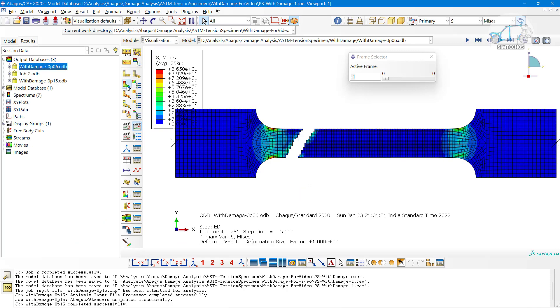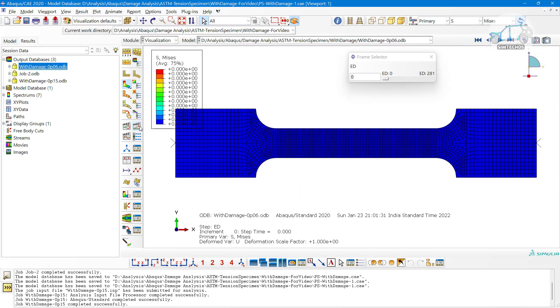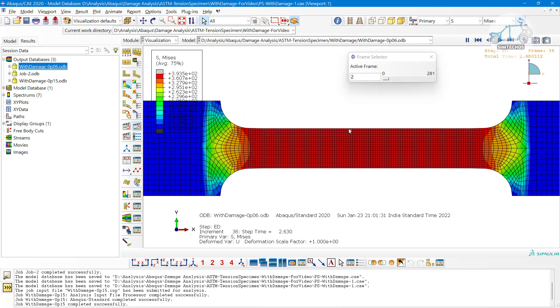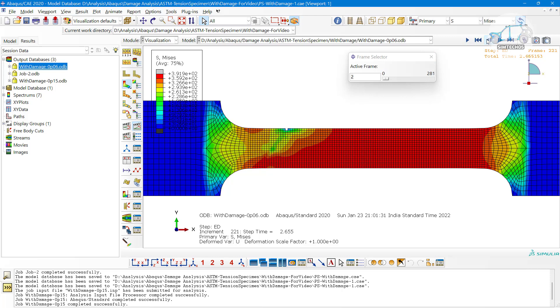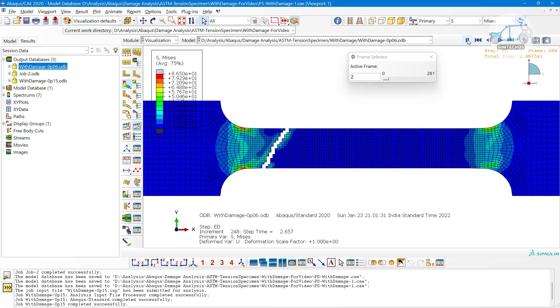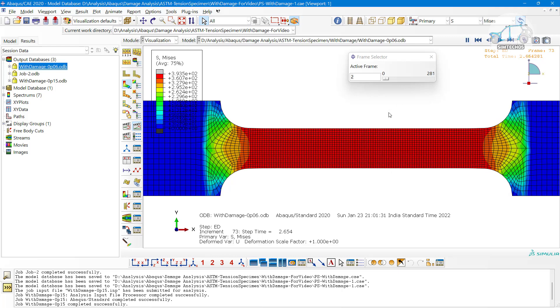So this is 0.15 for the second case. You will get a pretty accurate result. If you want to see the simulation behavior of both cases: in case one, once the load is sufficient enough to develop strain more than the fracture strain, element deletion takes place — but it takes place like a brittle material, because your fracture strain is very close to the plastic strain. This is not a good result because it does not match with any experimentation with a plastic material.